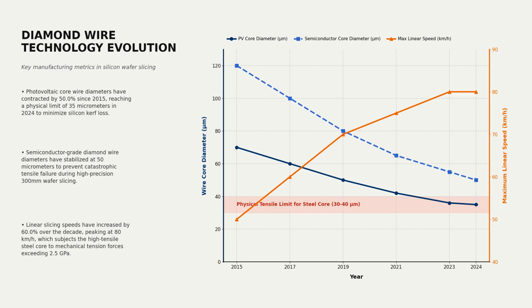The mechanical limits of silicon wafer slicing are determined by the tensile strength of ultra-thin steel wire. To minimize material waste, photovoltaic wire diameters have shrunk 50% since 2015, reaching a physical floor of 35 micrometers. At this scale, the wire must withstand linear speeds of 80 kilometers per hour. This mechanical environment subjects the steel core to tension forces exceeding 2.5 gigapascals.